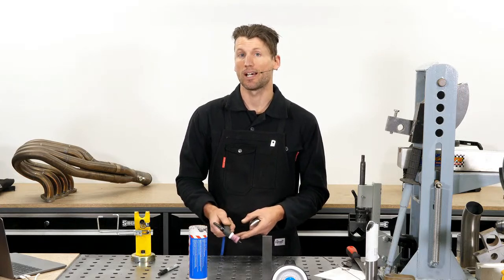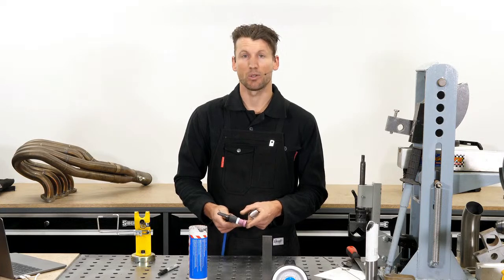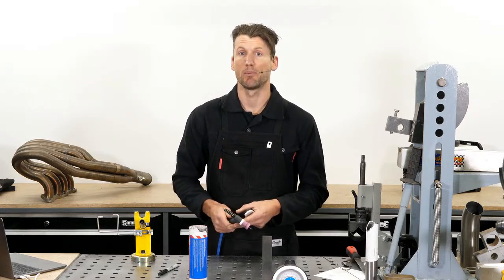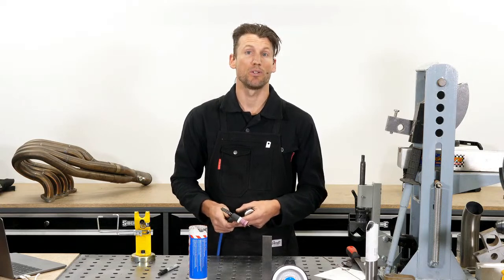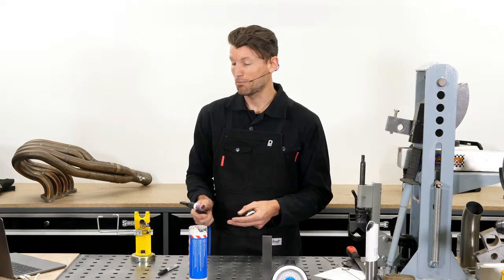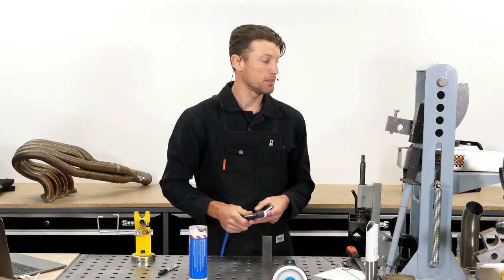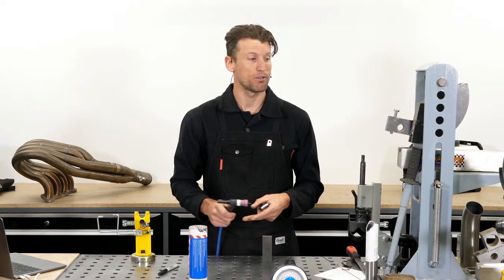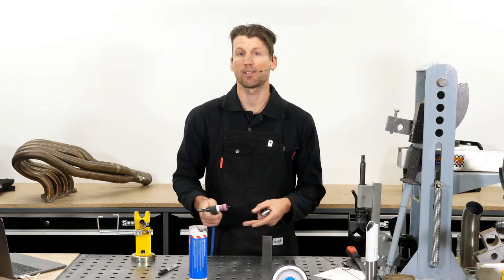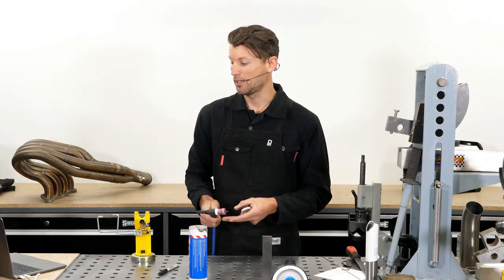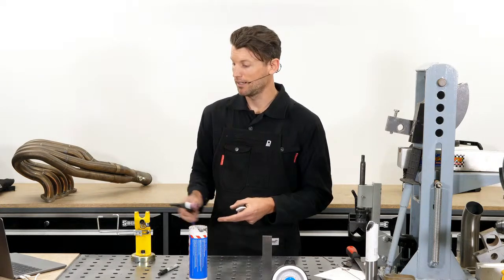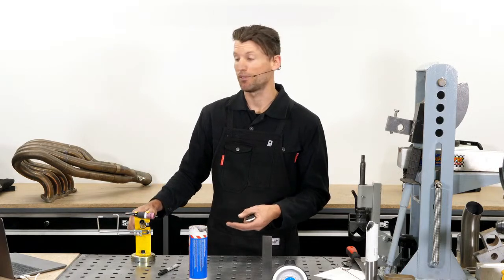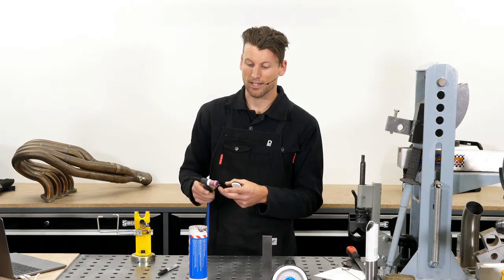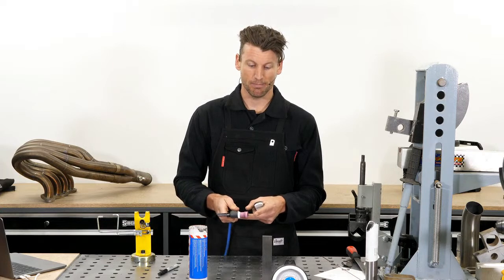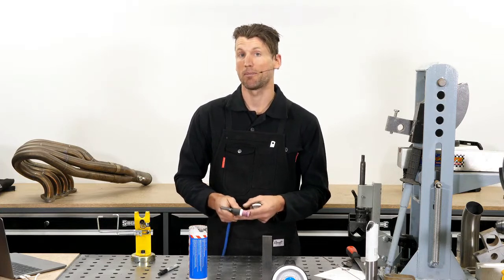One of the problems with scratch start, especially with TIG welding, is that you're basically contaminating the tungsten as soon as you start welding. Now, this might not be a huge issue for mild steel welding, but for any other materials such as titanium, which you can do with a scratch start TIG, but it's not recommended, or stainless, you will create some impurities in the weld, and it won't be as good as a high frequency start TIG. So I would recommend, if you're in the market for one, definitely upgrade to the high frequency start TIG, which will allow an arc to jump off of your tungsten onto the job without contaminating it.